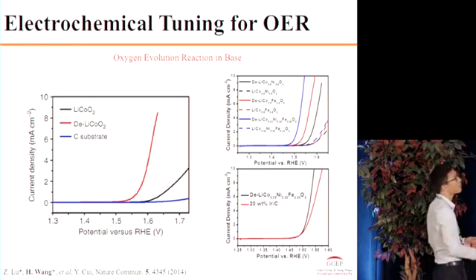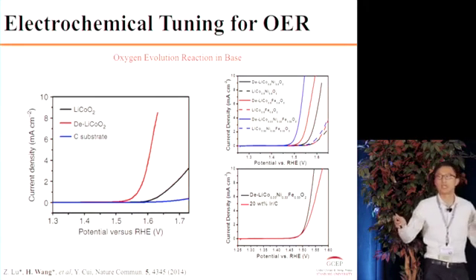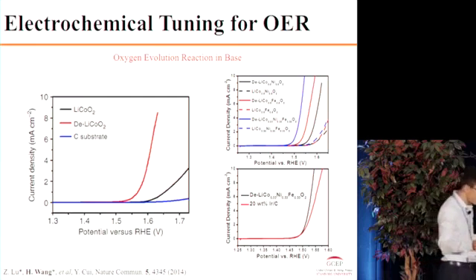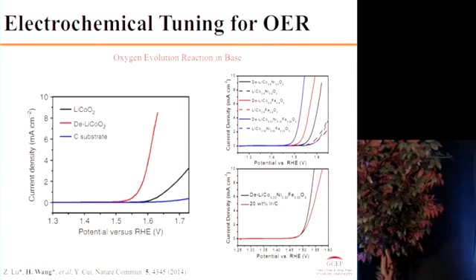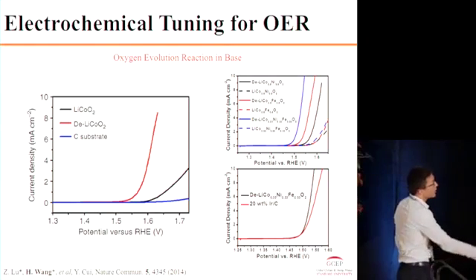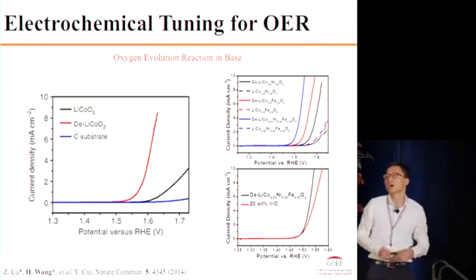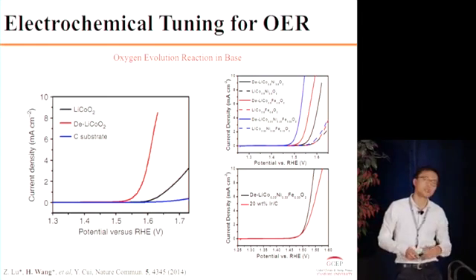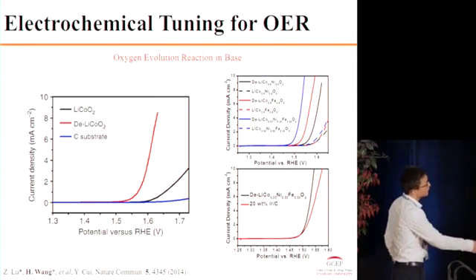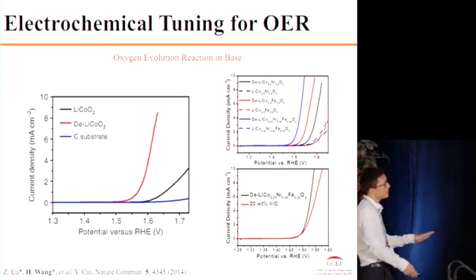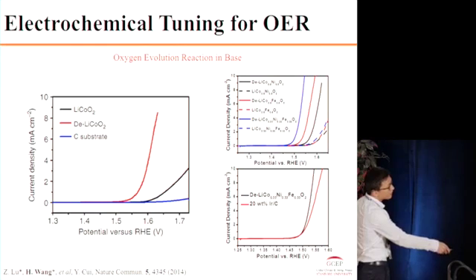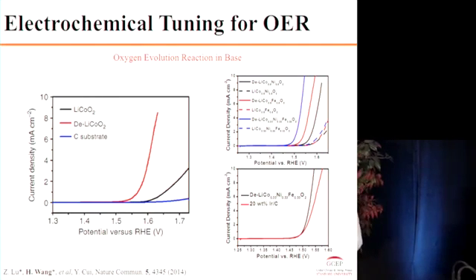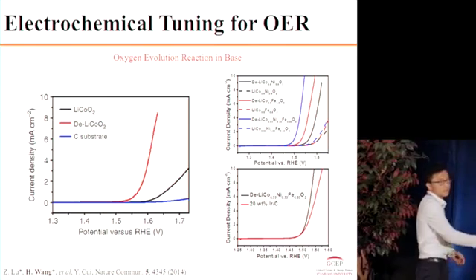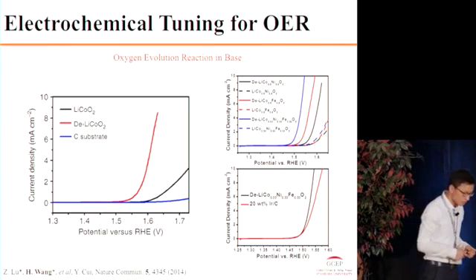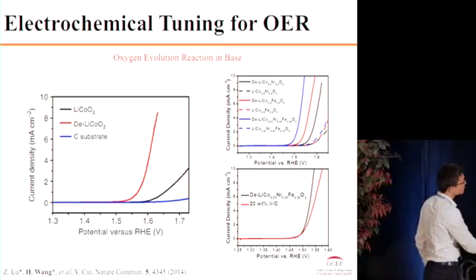And also, if we incorporate other transition metals into the lithium cobalt oxide material, such as lithium nickel oxide and lithium nickel iron oxide, actually we can see all of these materials after the extraction process, the catalytic activity is significantly improved. And the hero comes from the three-element combination, which has even better catalytic activity than the noble metal iridium. That is the benchmark catalyst of the oxygen evolution.